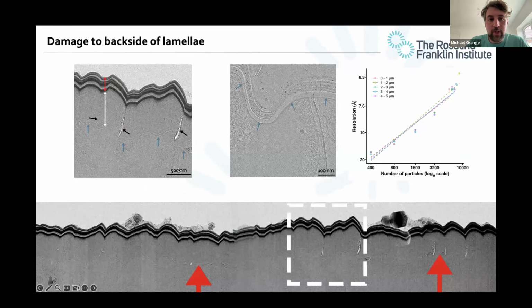The fun thing with the 60 nanoamp trench milling is that you can see here, for example, at the back of the lamella, you see this very large, so this is about a micron. You see a micron of amorphization. Now, in the material sciences world, amorphization is when you mill a crystal, what happens to the crystal? Does it stay crystalline, or does it become non-crystalline? When it becomes non-crystalline, that's called amorphization. We don't have the same kind of nomenclature for this experiment, but what we can see is on the right-hand side here, there's a bacterium with a double membrane.